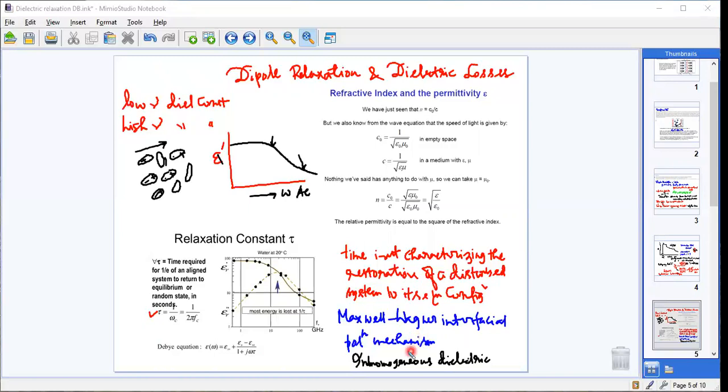The orientational relaxation frequencies vary over a wide range and may be strongly dependent on the temperature. In water at room temperature, relaxation occurs at about 3 times 10 to the power 10 cps, corresponding to a wavelength for electromagnetic radiation of 1 centimeter. In ice at minus 20 degrees centigrade, the relaxation frequency is of the order of 1 kc.